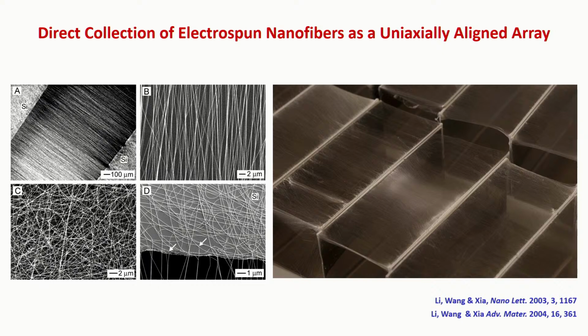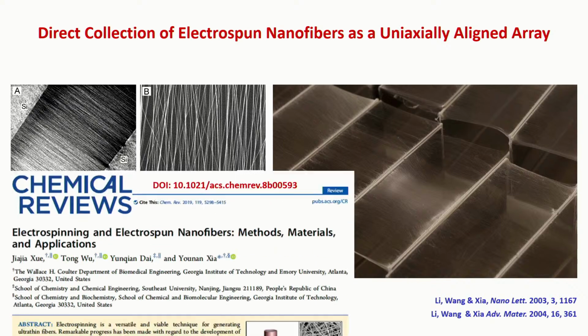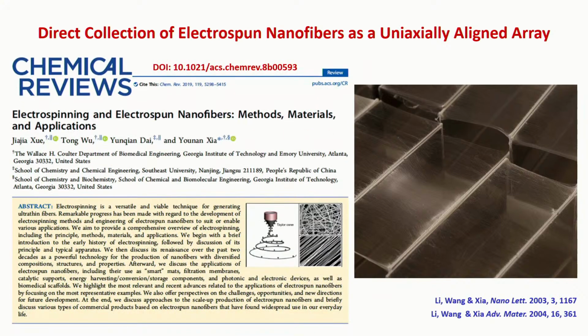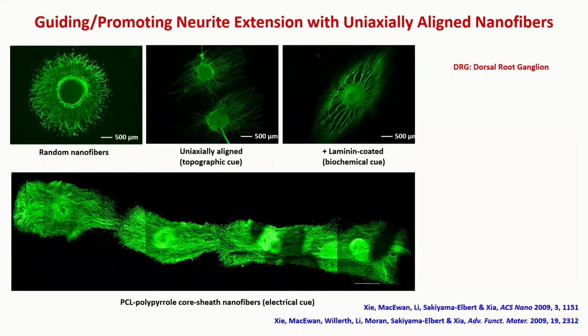This simple device is fabricated using a piece of metal. You take a piece of metal, you just bend it into a U shape. So these 2 edges basically can serve as the electrode to collect the fibers. The fibers will be stretched across these 2 edges. So you can have multiple of them stacked together, and eventually you can align the fibers over a pretty long distance. This is about 10 centimeters actually in this way. That can be aligned pretty easily. And for those of you interested in electrospinning and electrospun nanofibers, we have a major review article published 5 years ago. You can take a look at it.